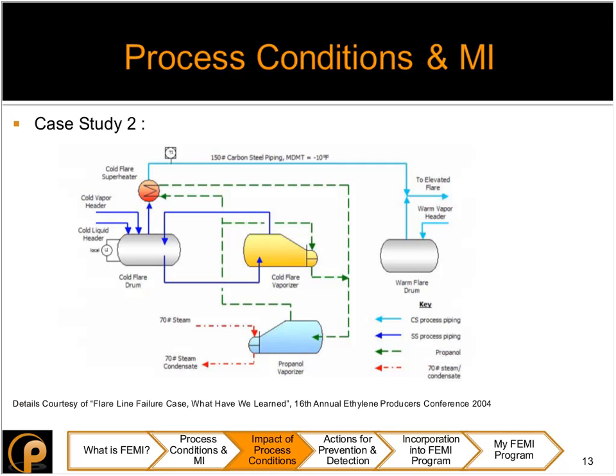Now, to better understand this, I'll go over a case study of a failure that happened at an ethylene plant in 2002. Describing the process overall, it was an olefins ethane cracker with a flow stream of demethanizer first and a back-end acetylene converter. As you can see on the screen, this is the cold flare drum, where the contents are vaporized and superheated using a closed loop propanol system, where heat is applied using 70 pound steam operating at around 270 degrees Fahrenheit, and heat is applied to the cold flare drum with the use of this cold flare vaporizer and this cold flare superheater that's in place.